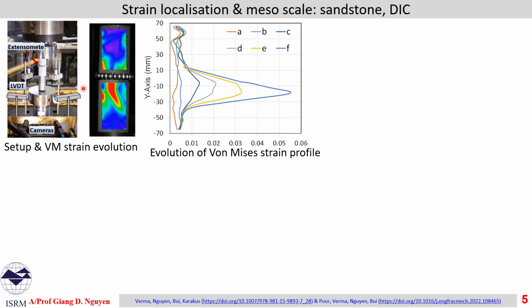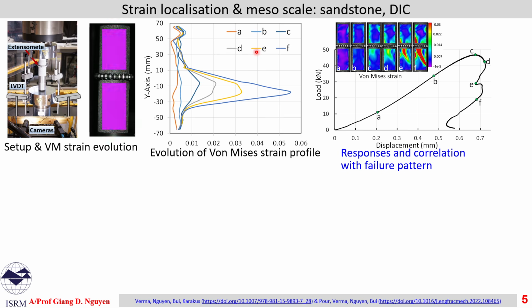So this is the ISRM standard or recommended test using the chain extensometer on the uniaxial compression of a sandstone in this case. If we are able to successfully control the test, the result will be shown later. We can see the strength evolution and in the end a shear band like this. If we plot the evolution of von Mises strength across the shear band at different stages, we can see such a strong inhomogeneity, well beyond the acceptable range for what is called homogeneous material behavior.